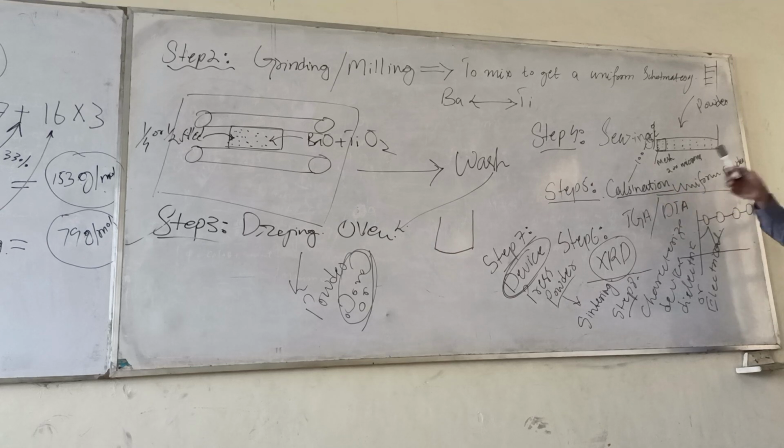calcine this powder. Put this powder in some sort of crucible, usually alumina, porcelain and different types of materials are recommended to process your material. Mostly we recommend alumina because it is stable up to 1100, 1200, this kind of crucible. They are chemically stable. Always use clean crucibles. Okay? The clean one.